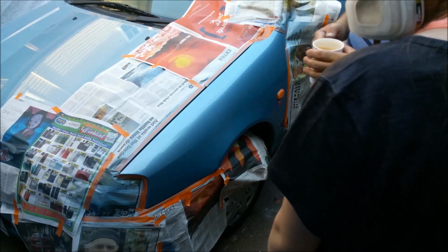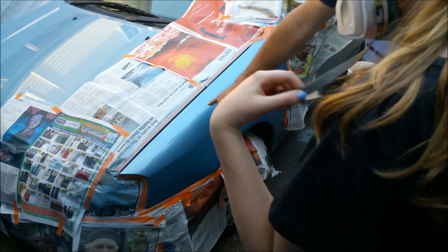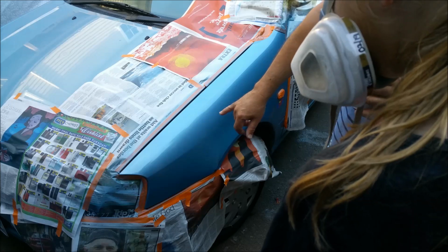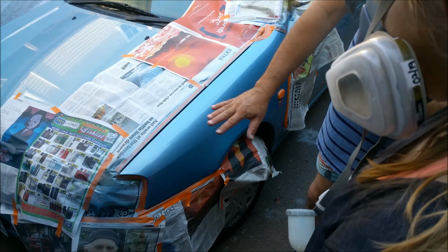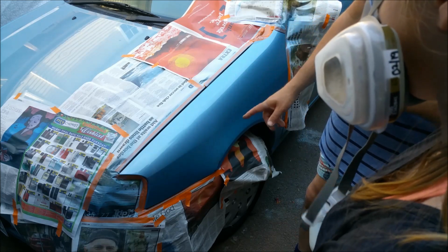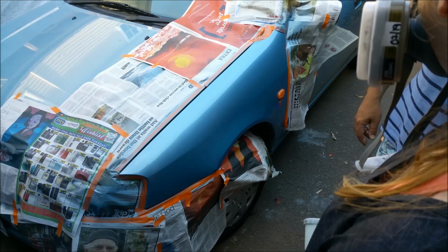It's got what's called orange peel. You see it looks like the skin of an orange, that's lumpy. What we'll do in a few days is get some wet and dry, 2000 grit, which is very smooth, and we run all that out, we sand it with water and wet and dry, and then polish it, and it'll be like glass. You've done that really, really well. I'm impressed.